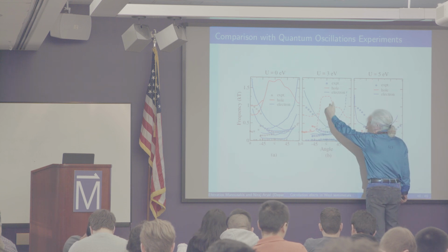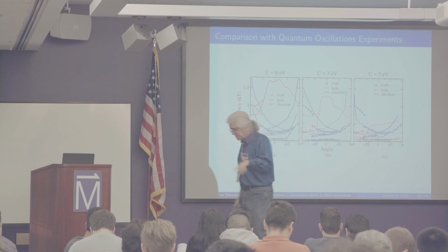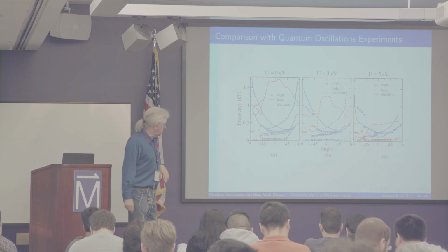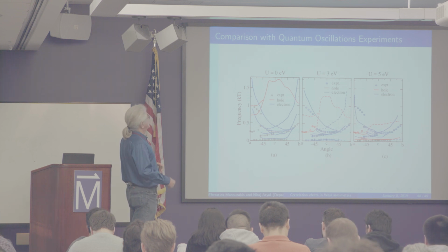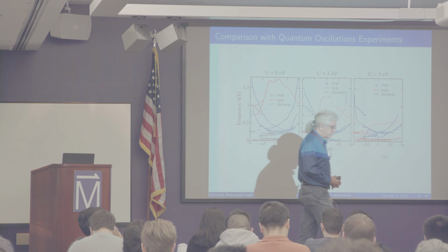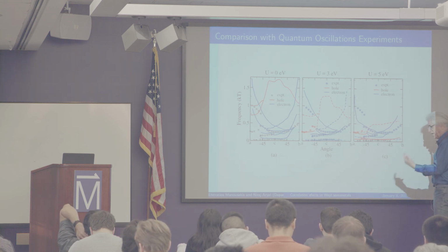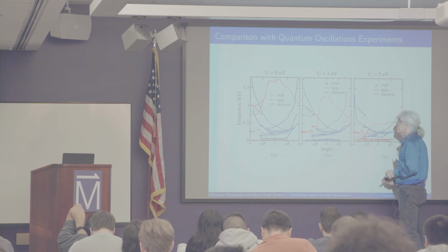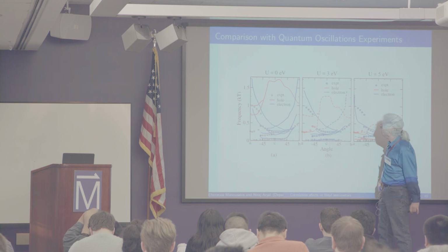These are pretty large frequencies, and that means that maybe there is more dissipation. By the time you go around once around the Fermi surface, the electrons lose steam. They don't exist anymore because, again, in the quasi-particle picture, you have to go into residues and see lifetimes. For how long do these quasi-particles exist? Do they have enough lifetime to go around the Fermi surface once? Maybe not. We are just doing GGA+U. These effects are not there.